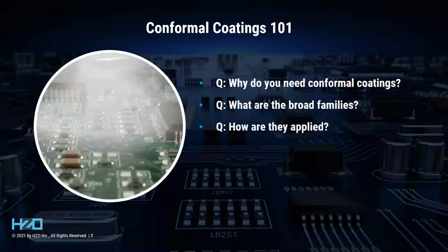How are they applied? We covered this briefly previously, but traditional coatings can be a 1-part or a 2-part. They're almost always a liquid. You can spray them, dip them, dispense them, and all of that can be done in line with your other manufacturing processes. But it does leave a risk of bubbles, voids, and wetting problems. Parylene is the outlier here. It's a vacuum deposited material, which is by necessity a batch process, but the vacuum coating does have strengths, which we'll cover in the next few slides.